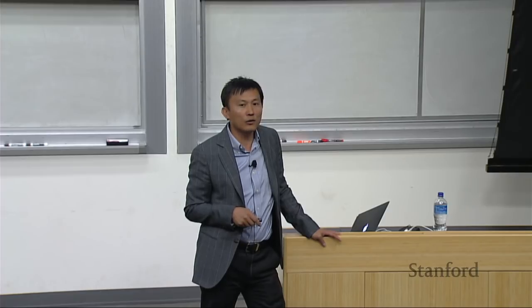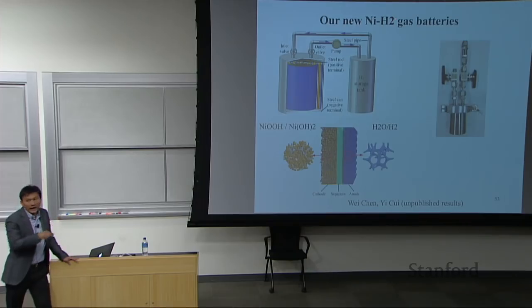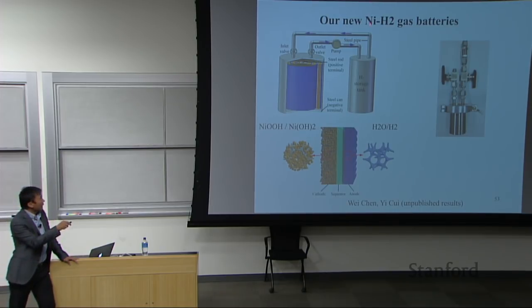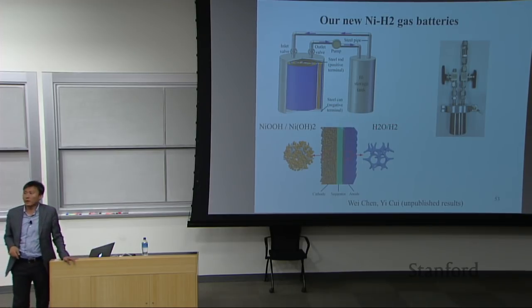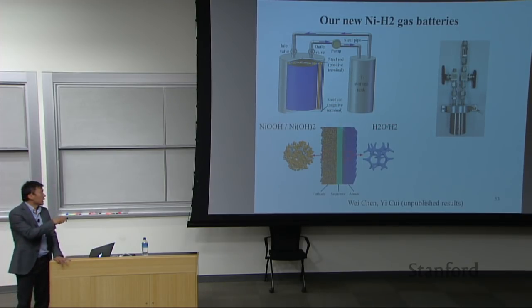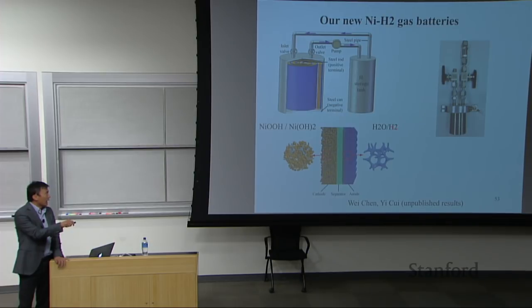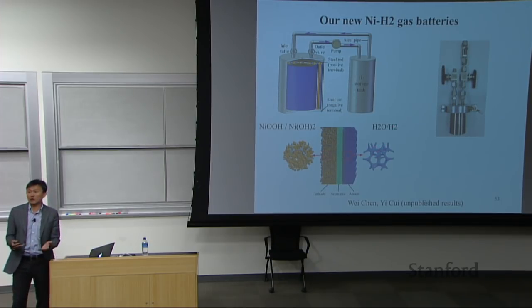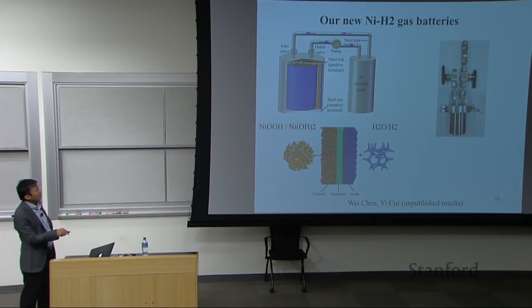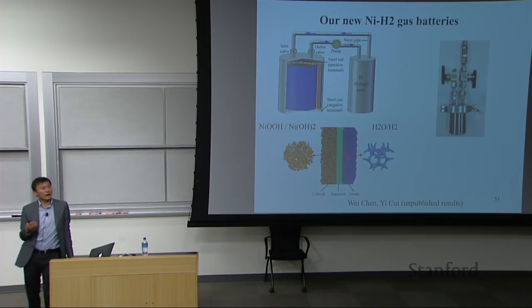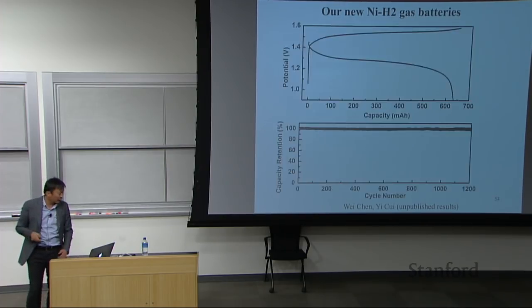Nickel metal hydride uses hydrogen stored in the alloy. Here we only use gas. And basically one is a solid electrode, that's a nickel oxyhydroxide and nickel hydroxide cycling back and forth during charging. But the anode is hydrogen and water. And building up this battery is simple. So it's taking the nickel hydroxide and water and putting the catalyst for the hydrogen into this electrode. You build it up in the discharge state. Once you charge it up, you generate hydrogen gas and put it into a tank. So it's also an idea of semi-flow battery. Half is solid, the other half is gas. You only flow the other half. Very simple construction. And this has a very long cycle life.